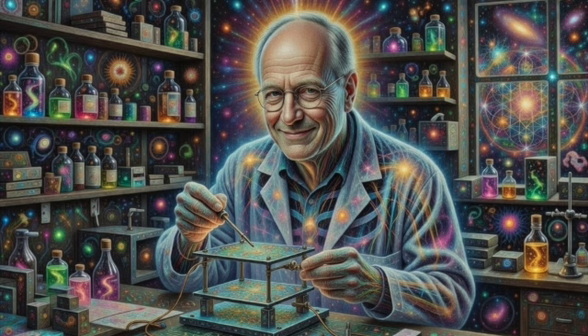But the most exotic solution involves manipulating the force itself. In 2009, a team at Harvard University, led by Federico Capasso, demonstrated that the Casimir force can be made repulsive. By choosing specific materials and immersing them in a liquid, they changed the way the fluctuations interacted with the surfaces. They used a gold-coated sphere and a silica plate submerged in bromobenzene. Because the dielectric properties of the liquid were between those of the two solids, the vacuum pressure pushed the objects apart instead of pulling them together.